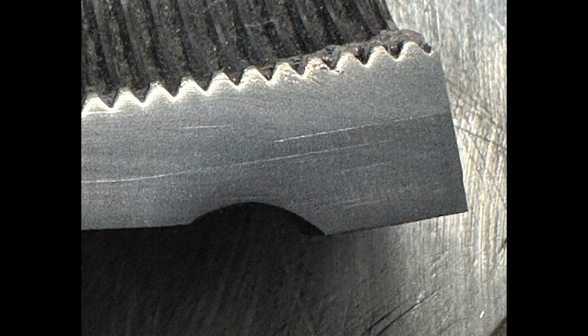But the penetration went all the way down and completely fused the root. It's difficult to see in this cut and etch, and I actually tried to do it multiple times to really get a discernible weld, and in this case it just was too difficult. So you can see the left edge of it, but needless to say, there's no lack of fusion. There is some penetration, and this is 100% basically as strong as you can get. It just needs another pass on the top.